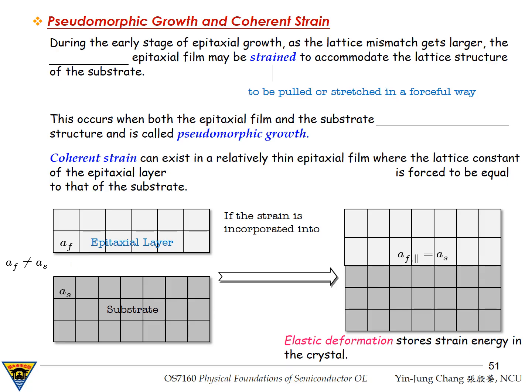At the very early stage of epitaxial growth, when the film is still relatively thin, something interesting can happen. Instead of immediately forming defects such as misfit dislocations, we're going to talk about that later, the film may elastically deform in order to adapt to the lattice structure of the substrate. In other words, the atoms in the epitaxial film are stretched or compressed so that the spacing between atoms parallel to the interface becomes equal to that of the substrate. This situation is called pseudomorphic growth.